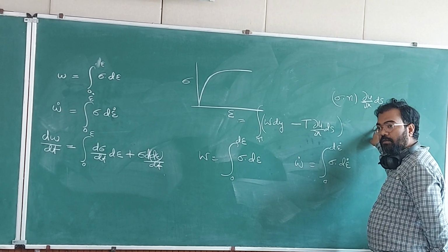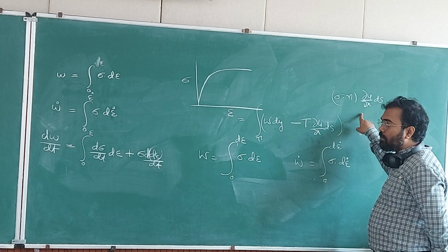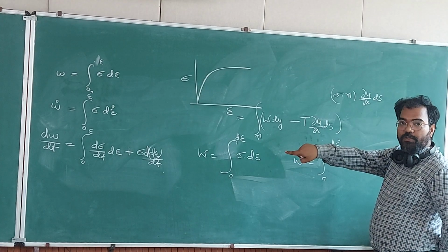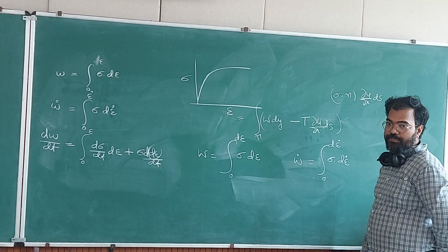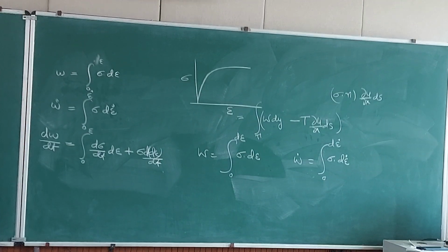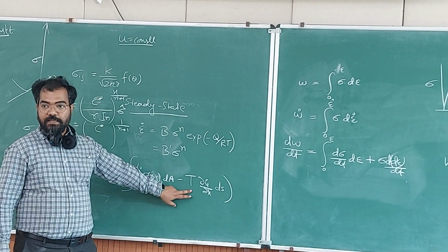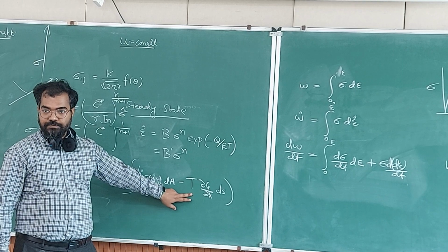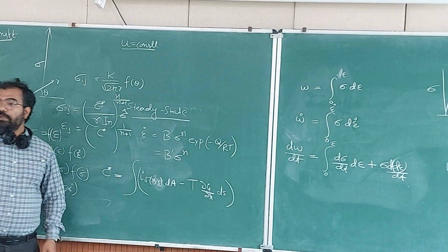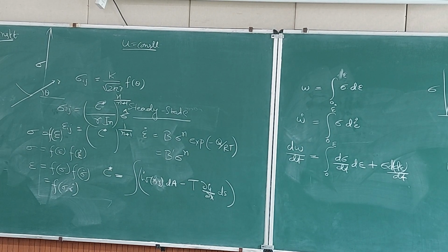So you see that the derivative of this is not going to be equal to what you are getting in C star, where you have only two terms. You don't have the term where the derivative of traction is taken, where the derivative of sigma is taken. That term is missing. So these two quantities are not the same, therefore they are not defining the same thing.